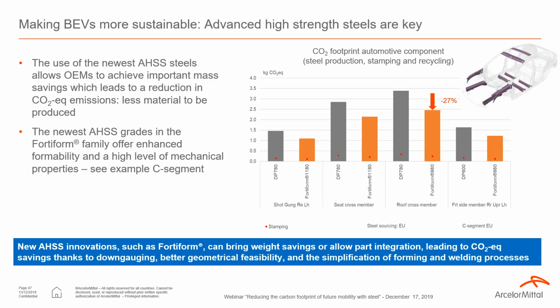Here you can see an example of a C-segment roof cross member. We were able to achieve up to minus 27% of CO2 equivalent emission. This is possible thanks to the very high mechanical properties, which help to reduce the thickness, but also to enhance formability, which gives more flexibility to designers to manage the crash in a better way, and to continue to further reduce the thickness of the part to keep the same crash properties. So new advanced high strength steel innovations such as Fortiform can bring very interesting savings thanks to higher mechanical properties and best-in-class formability for cold stamping.